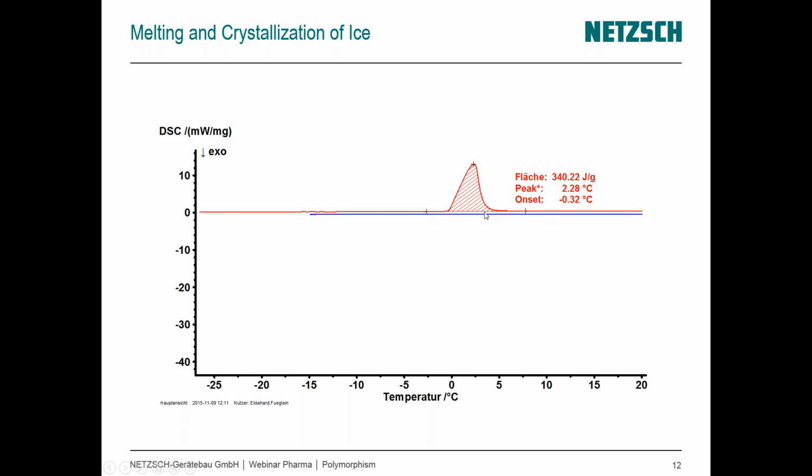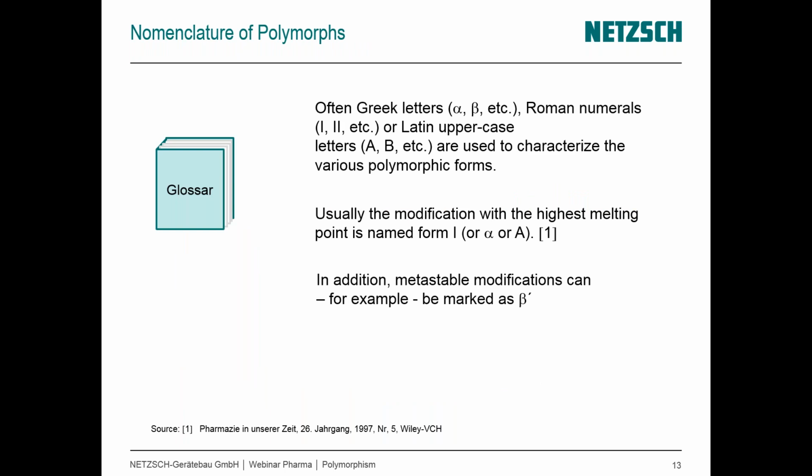But then what we see under cooling is we get the material all the way down here to negative 15 degrees Celsius, and there's still no crystallization taking place. Again, that melting is a thermodynamic process. The cooling is a kinetic process, and this is something that you might have seen before. This is known as supercooling. We reach here some critical point where there's the onset of crystallization, after which point we have a small seed crystal, and then that provides a lattice, after which the rest of the water molecules, which are already well below their actual freezing point, then arrange themselves around that, and we get a very rapid cooling.